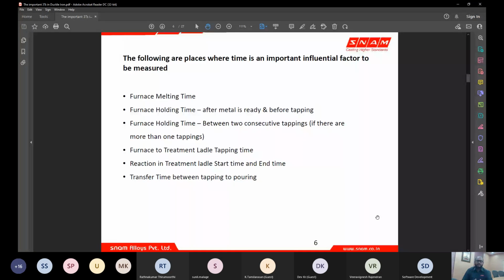What happens if there are 2 or 3 different lines, and there can be a slight increase in the tapping time? Maybe every tapping should be say 20-30 minutes apart. Say you tap and then you pour, your tapping time may be 20-30 seconds or maximum 1 minute, and then you pour up to 10 minutes. So your tap to tap time will be an average of 10 to 15 minutes. In some instances it can become 15 minutes, or 20 minutes or 30 minutes because of some molding line breakdown.